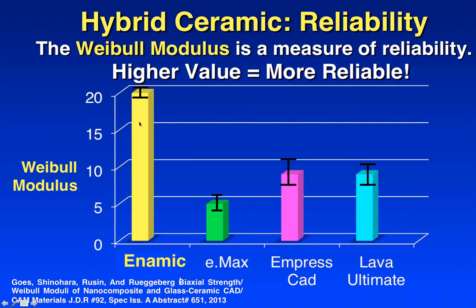So if we look at a comparison of the Weibull modulus of Enamic versus other materials, this data that was generated by VITA is almost exactly the same as data that was generated by 3M, and this is an abstract that's being presented at the International Association for Dental Research in a few weeks out in Seattle. The Weibull modulus of Enamic is around 20. We have different iterations that we can get up to 40, which is just incredibly geeky, exciting stuff for ceramic people, because you never get something that high unless it's a really, really bad material that fails at a few megapascals.